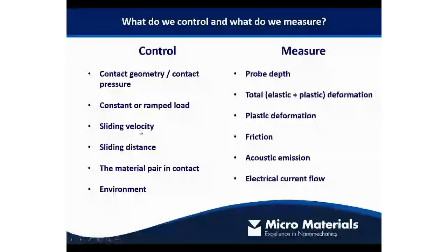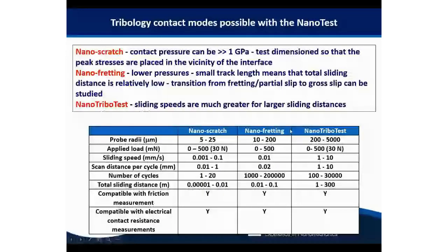What do we control or measure in nano and microscale tribology tests? Well, we can control the contact pressure by controlling load and contact geometry. We can control how we apply the load. We can ramp it or have it constant. We can control sliding velocity, we can control sliding distance, we can change the material pair that are sliding. Often we use a diamond probe, but that isn't fixed. We could use a steel probe or whatever material you wanted to use. And we can change the environment. As we've just seen, environment is very important in tribo systems. We measure usually the depth of the probe into the material, so we get a view of the total deformation, also plastic deformation itself. Friction acting on the test probe, acoustic emission, and electrical current flow are other things that we can monitor in addition to these standard metrics.